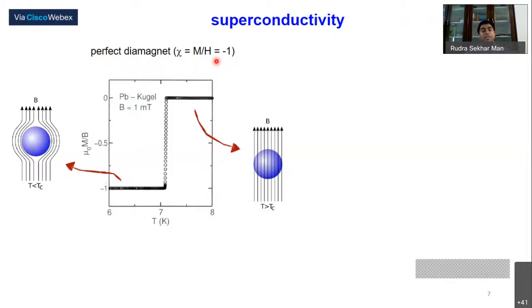That means if we apply a magnetic field, the magnetic field lines are somehow expelled. Initially you are below TC, so you should be in the superconducting state. Then you apply a magnetic field, and your material in the superconducting state expels whatever fields were inside, outside. And if you measure the magnetization, this is the curve which you get. This is also measured with lead. Lead is also a superconductor, with a TC of 7.2 Kelvin. Then you can see suddenly there is a jump, and that is exactly -1. That is called a perfect diamagnet. Otherwise every material normally has a weak diamagnetism, which is negative but not exactly -1, and that is the very peculiar example.